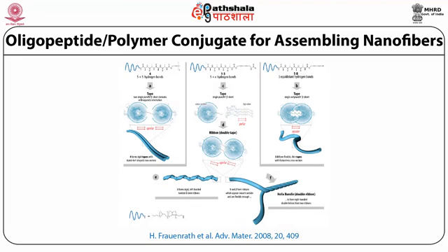One is case 4, where both sides of the diacetylene are flanked by the polyisoprene block and also the oligopeptide block. This eventually has hydrogen bonds formed on both sides, and this forms a tape-like structure through parallel beta sheet domains with opposite orientation. In the case of 1, 2, 3, they have the same plus additional hydrogen bonding from the other side, and they form a single parallel beta sheet like structure.